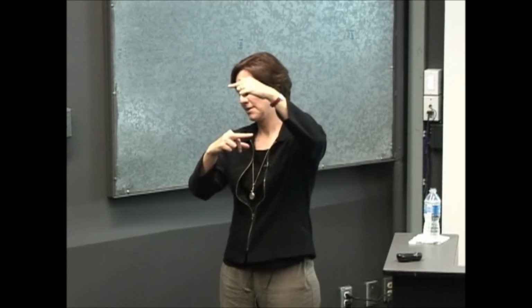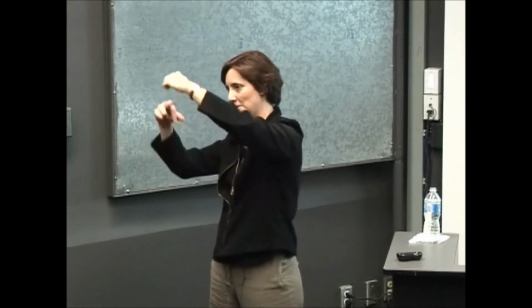I would love to have some help understanding that, but it's a very interesting result. And we have some interesting results, frankly, with the core-shell systems too. As a function of the shell thickness, what we're seeing electrochemically is that the gap is not really changing, but that both the valence and conduction bands go down in energy and then up again as we increase the shell thickness. These are brand new results, and we're trying to understand why that's happening. So if you have any ideas, put them in the chat. A couple of interesting results.